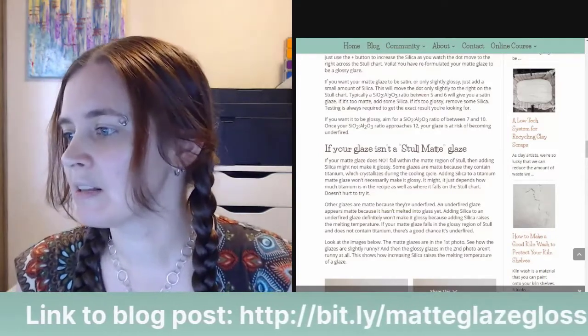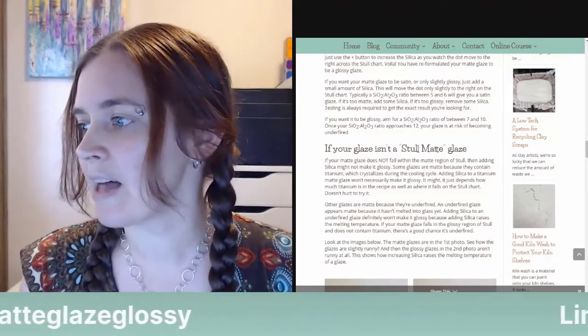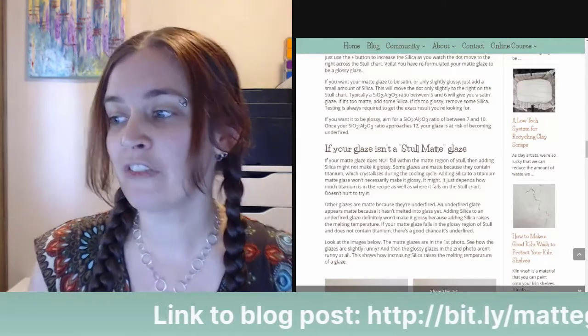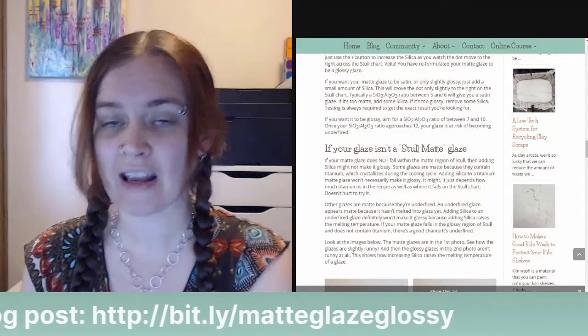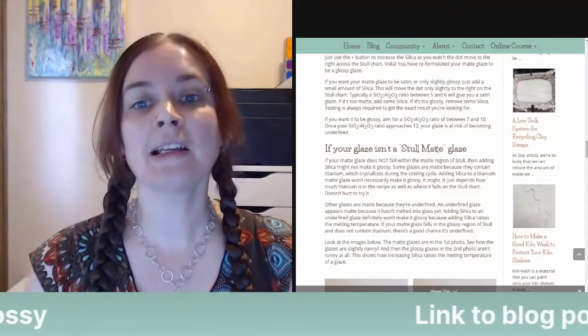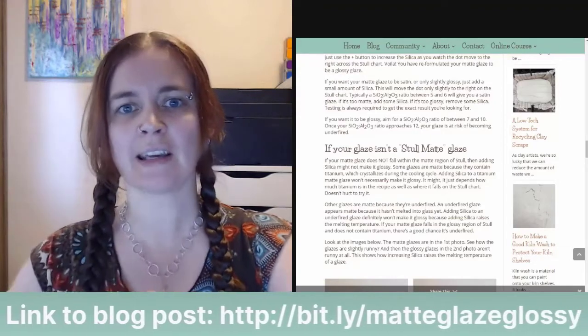So the question is, I've made glazes glossier by raising the cone from 5 to 6 or by soaking at the last firing cycle for 30 minutes. Does it make sense, to get a more matte surface, to do the reverse by lowering the cone and making the cycle faster, so having a quicker firing cycle? Yes, so I don't recommend lowering your firing temperature in order to keep that glossy glaze matte.